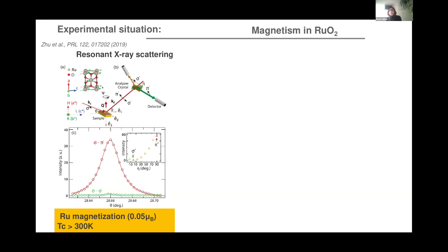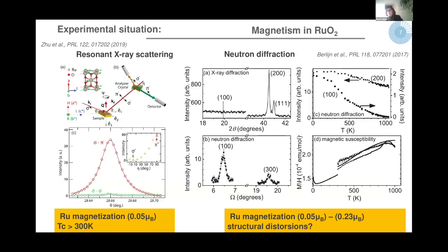On sublattice A along the Z direction it goes parallel to Z, and then on sublattice B it's anti-parallel. The way they were suggesting the presence of this magnetic order is, if you look here at the intensity as a function of the angle of the different polarizations, analyzing this intensity peak, they were deducing that the ruthenium had a magnetic moment that would show ordering below 300 Kelvin, and the magnetic moment is rather small, 0.05 mu Bohr. So this was one of these experiments indicating that indeed ruthenium dioxide orders in an altermagnetic fashion.